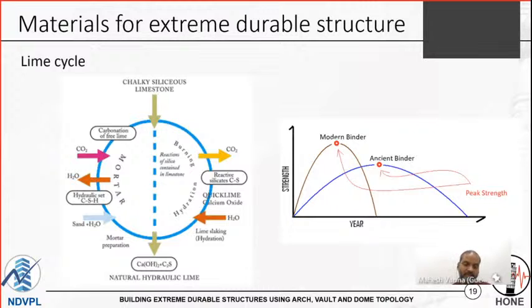C2S gives us long-term strength and C3S gives us early strength. And when we check the cement strength, it is at 28 days. We don't have any concern about 3 months, 6 months, 9 months, 2 years, 5 years. We are too much focused on 28 days. Sometimes I get puzzled, who invented this number 28? Why is it 28, not 30? At least a month. Maybe it must have been February or something like that when somebody said, test it after 1 month. But whatever the reason, we are testing it at 28 days. And we consider that to be a datum strength.